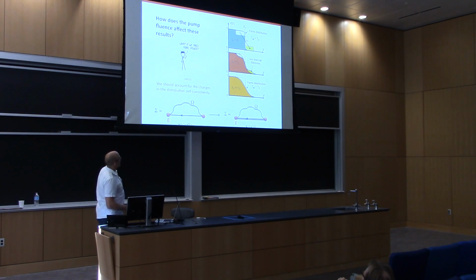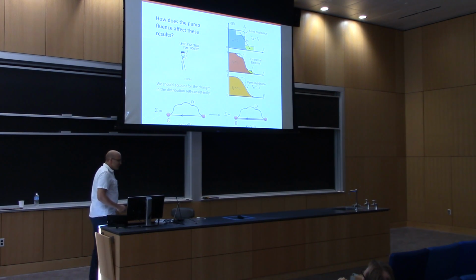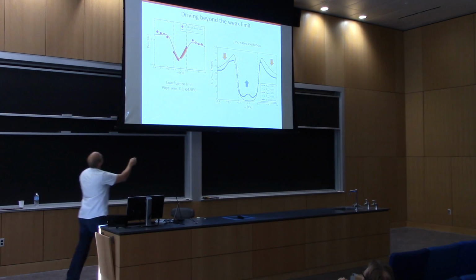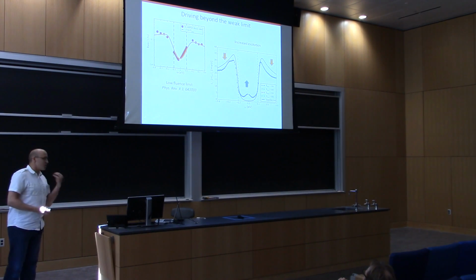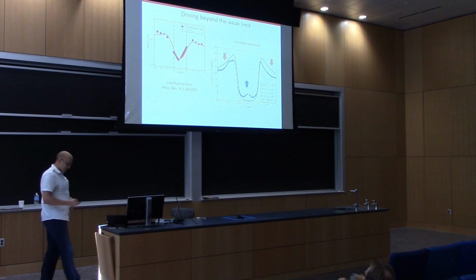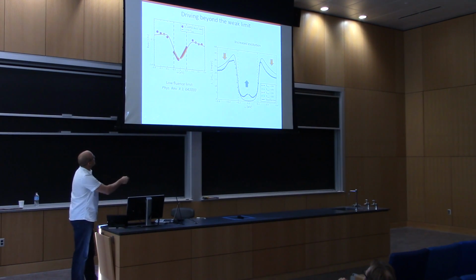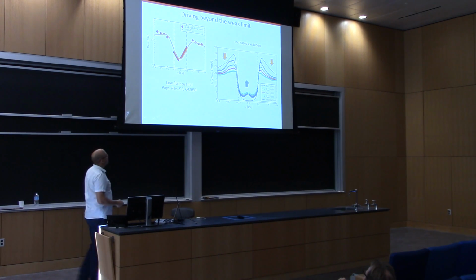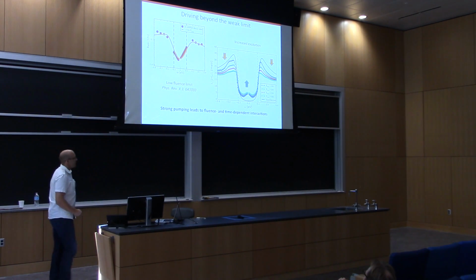So we should really account in our calculations for the changes self-consistently. For the theorists, that means I am now doing the self-consistent Born approximation. And what this leads to is changes. So here are our results again, in the limit where you are at such low fluence that you are not affecting anything at all. And now we're going to turn up the fluence, and we're going to take care of this redistribution of quasiparticles. So here are the same sort of things where we fit 1 over tau. And Jim showed this as well, where as I increase the fluence, I end up with changes in the scattering rate. Excuse me, changes in the population decay rate, because that's what these are.